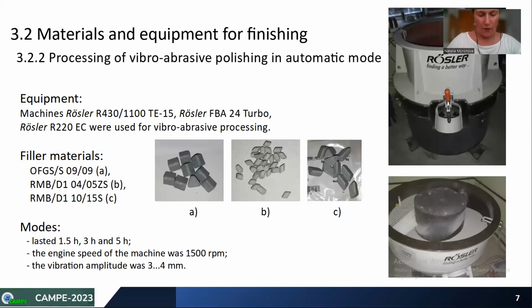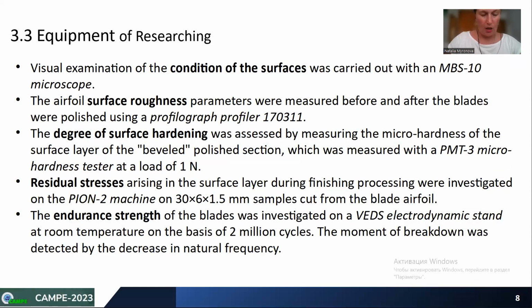The finishing processing of examined blades was also carried out in automatic mode using vibro-abrasive machines. Vibro-abrasive processing with different filler materials was carried out with the specified modes. The following investigations were carried out. The condition of surfaces, the airfoil surface roughness parameters before and after polishing, the degree of surface hardening, residual stresses arising in the surface layer during finishing processing, and the endurance strength as the main operational parameter of blades.